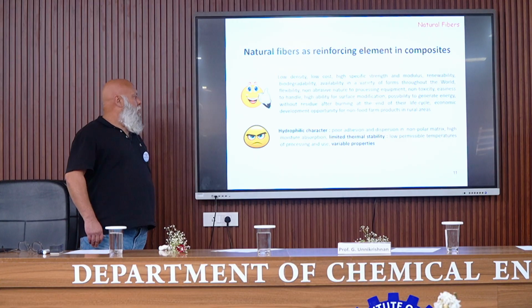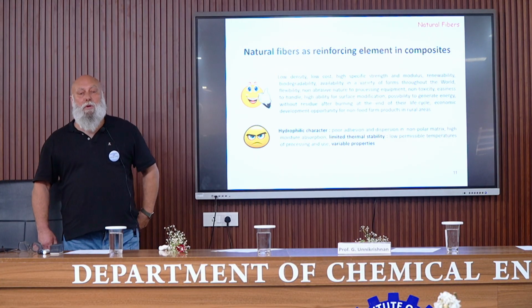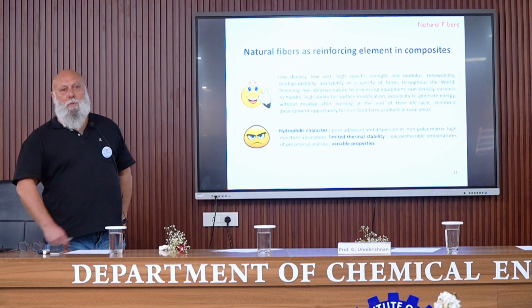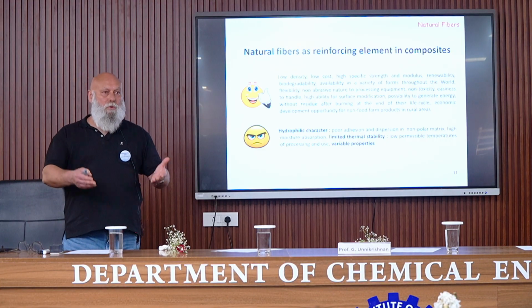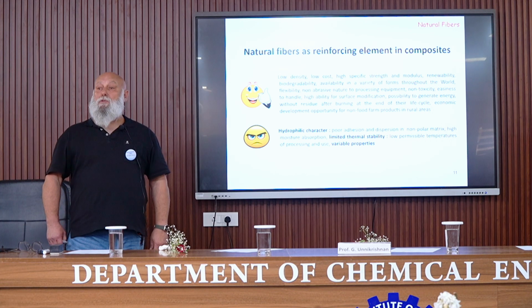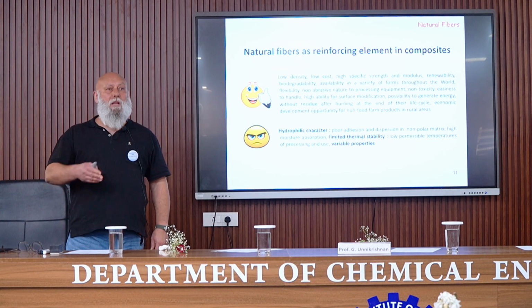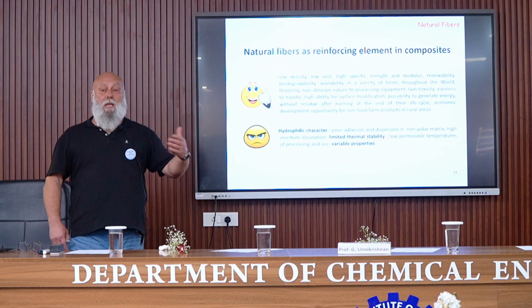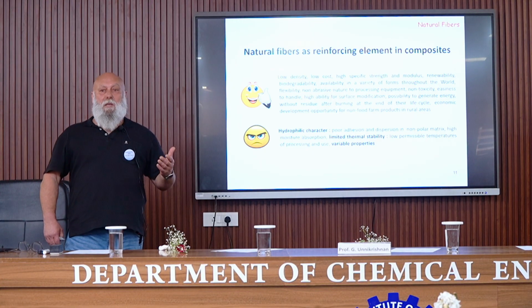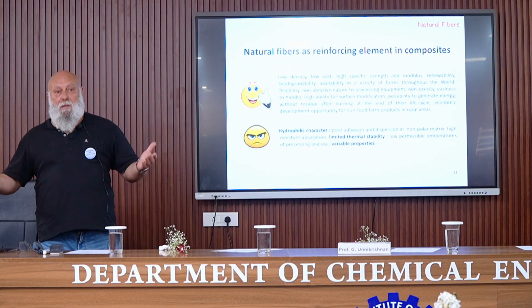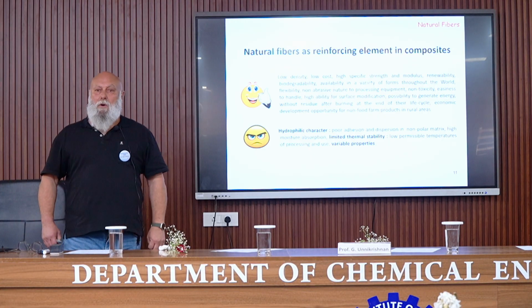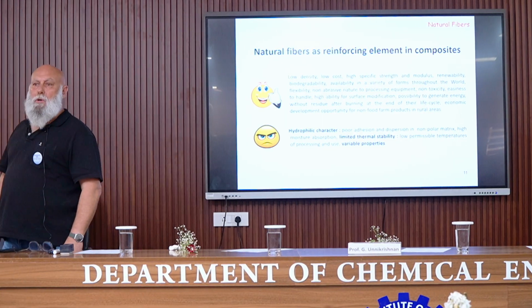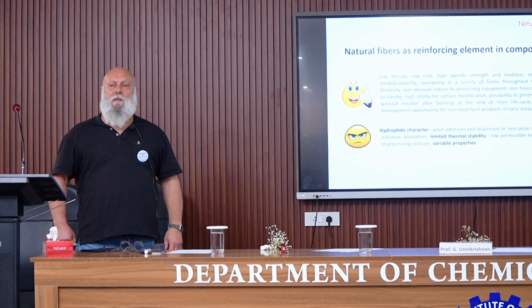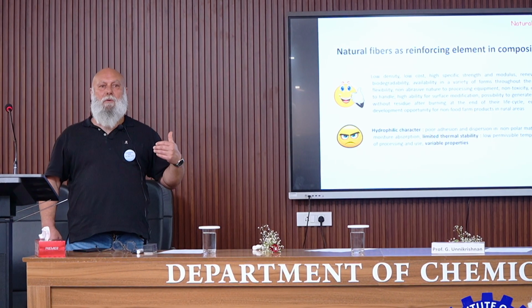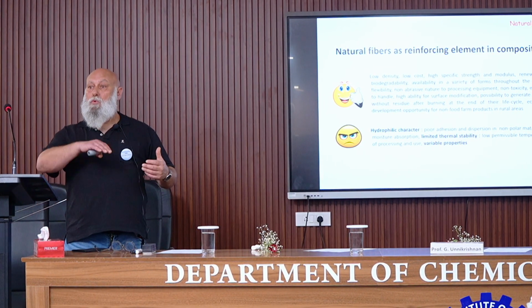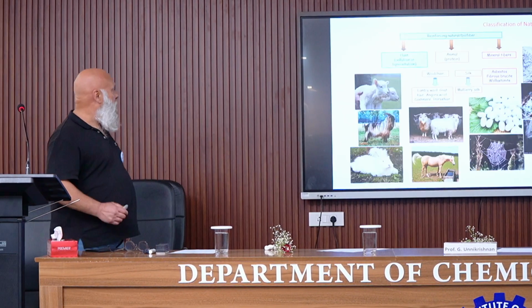Another drawback is variable properties. We'll see later that the properties of natural fibers depend, of course, on the source of the natural fibers, but also on the climatic conditions, the nature of the soil, the age of the plant, and so on. So you have variable properties, but it's a natural product. Usually, in biocomposite industries, a mixture or blend of fibers that have been harvested during the last 5 years is used just to homogenize the properties.